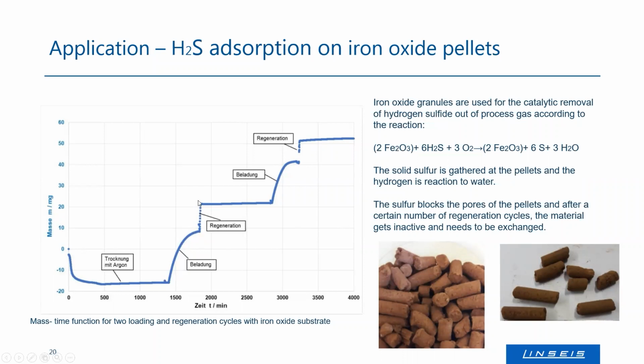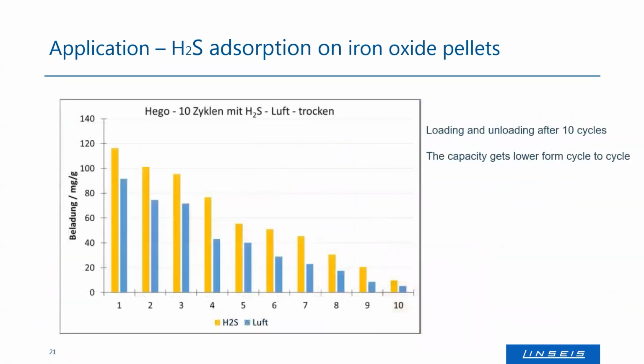Then you have a regeneration step. There you're bringing in some oxygen. The reaction goes backwards. The iron oxide is regenerated. Sulfur is collected at the surface. And then you can do another loading cycle, and regenerate again for more loading cycles. The purpose of this experiment is to check how many cycles you could use these pellets. So you could monitor the loading and unloading by oxygen regeneration for multiple cycles.